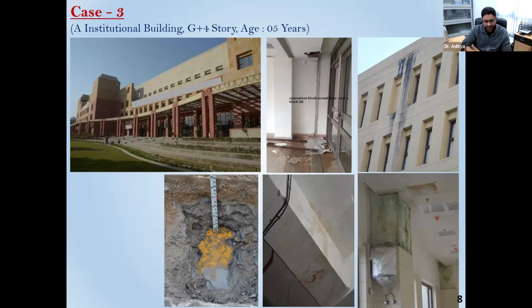So in this particular case, I can say that the build quality was good. The maintenance team was also very sincere. They were doing well. The material used was fine. But just because of one mistake, that while doing the waterproofing, they missed the waterproofing itself, and they provided a thermal insulating puff followed by a thin polythene layer and followed by a 6 or 8 inches PCC for the sloping. So that's what they have done.